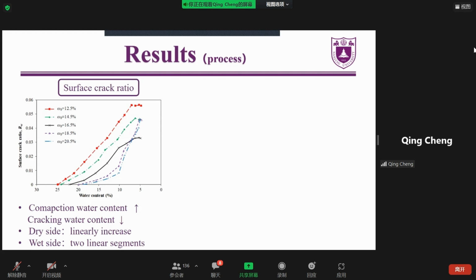This is because the cracks in the samples compacted on the dry side and at optimum water content appear in the void between aggregates, while the cracks in the samples compacted on the wet side appear in the void between the soil particles. The larger pore diameter develops a smaller suction, resulting in a higher amount of water retained in the soil. As a result, a higher cracking water content can be observed for the soil samples compacted on the dry side.